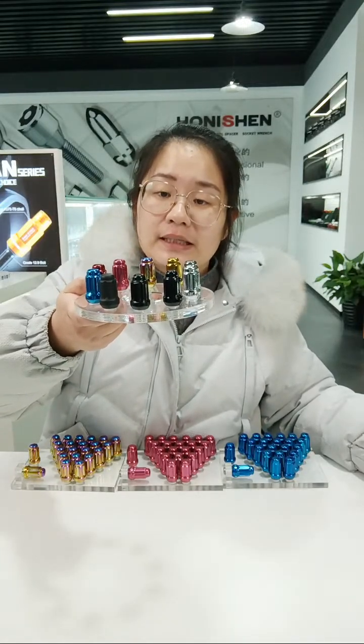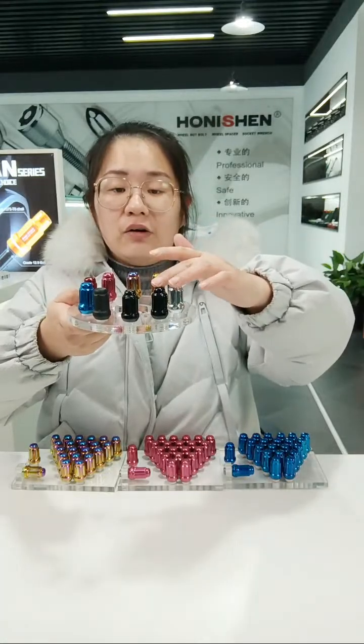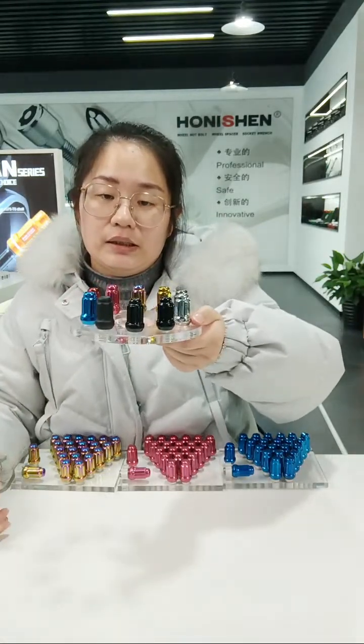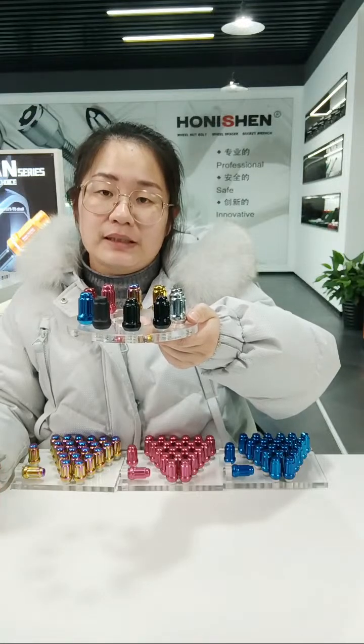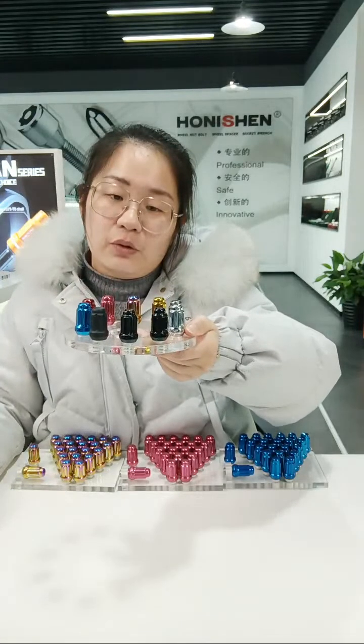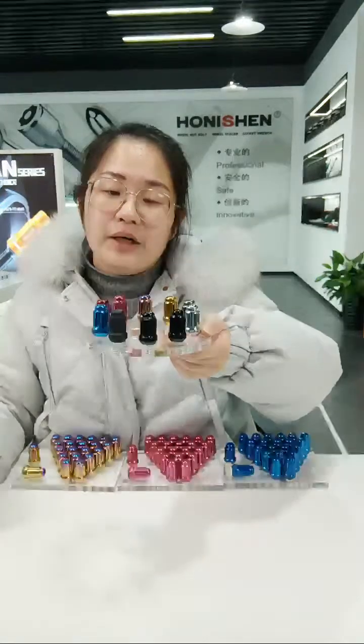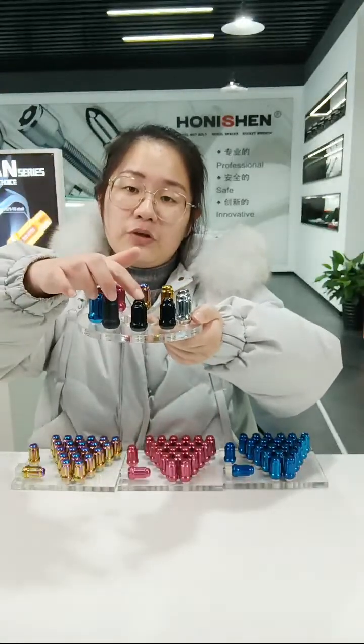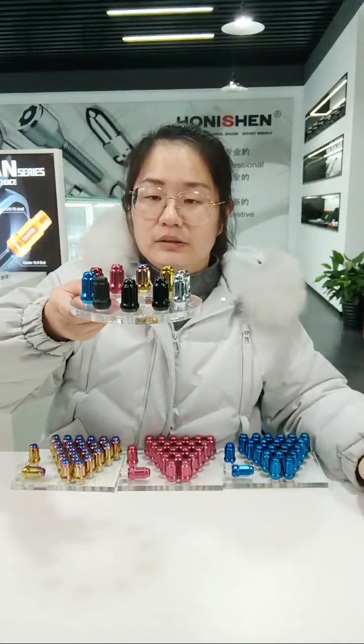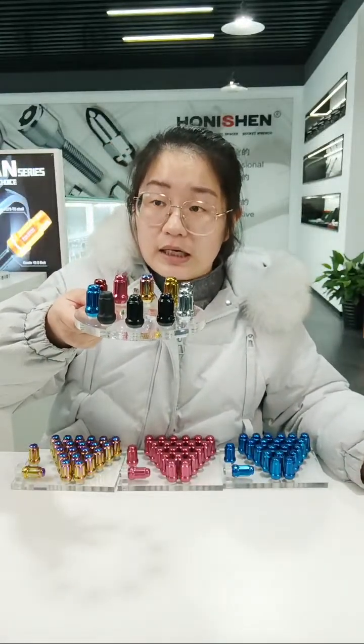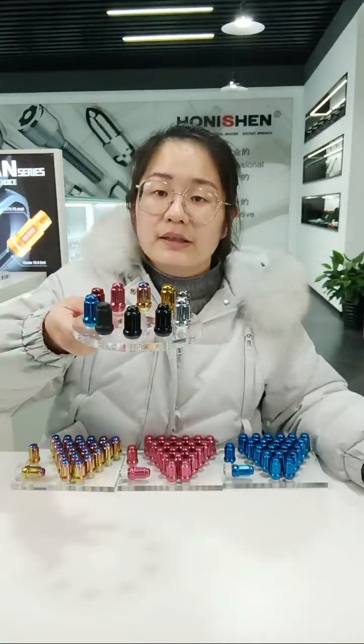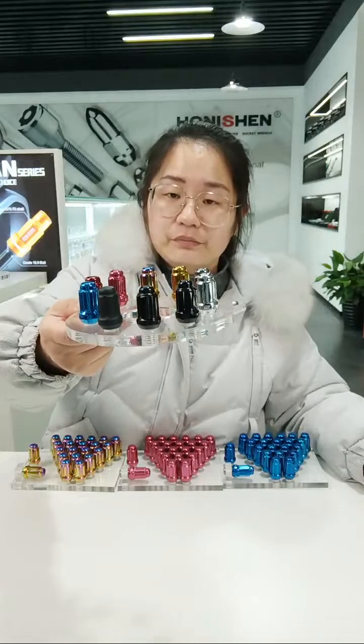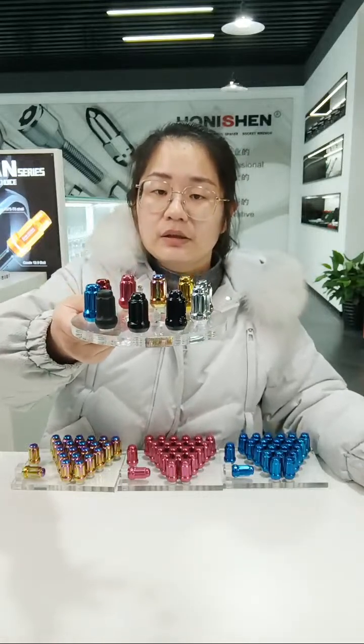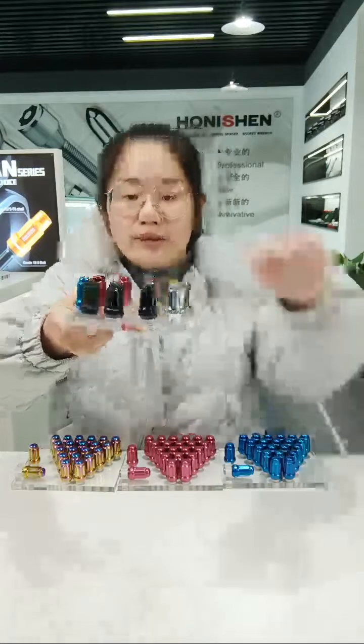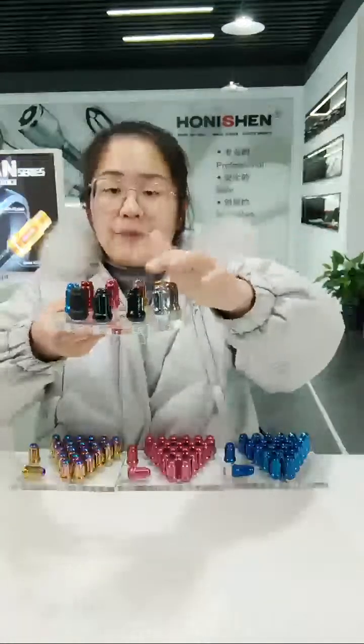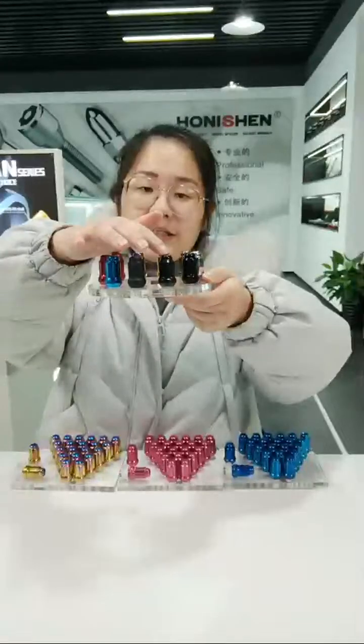Second, the color fastness is different. For black chrome and matte black, the anti-rust is good and the color fastness is very good. Even if you knock it, there is no trace on the nuts. For black electrophoretic, the color is paint. When you knock it, the color will come off. Third, the color brightness is different. Black chrome is bright, and for black